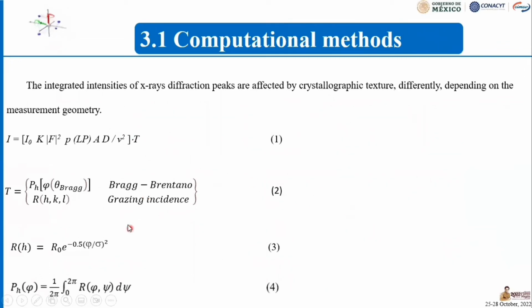Computational method. The integrated intensities of the X-ray diffraction peaks are affected by the crystallographic texture, and these depend on the measurement geometry. Here, I0 is the incident beam intensity, and K is the instrumental constant. F is the structure factor, P the multiplicity factor, L the Lorentz polarization factor, A the absorption factor, and D the Debye-Waller factor. V is the cell volume and T is the texture factor.